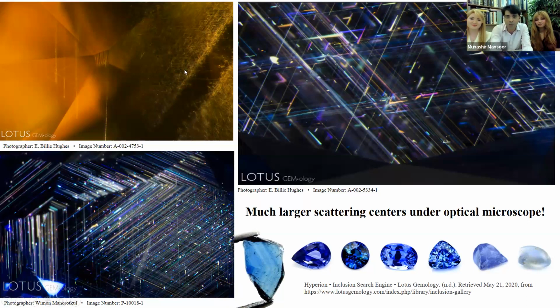And even worse, if they're very scattered, very small in size, then you have these opalescent sapphires that have recently become quite trendy for some reason that I do not understand. It's actually very pretty when you think about it. I don't find them pretty, but anyway, those are perfect for heat treatments, because these opalescent sapphires tend to have very small crystals of rutile in them. And since they're very small crystals, you can dissolve them in the sapphire much more easily. But we will come to that very soon.